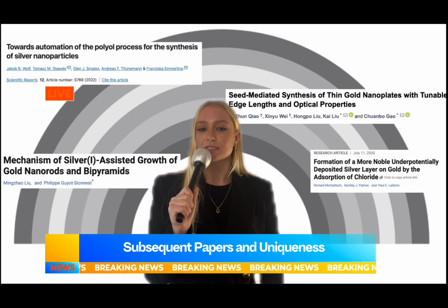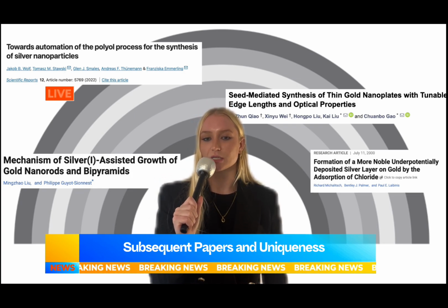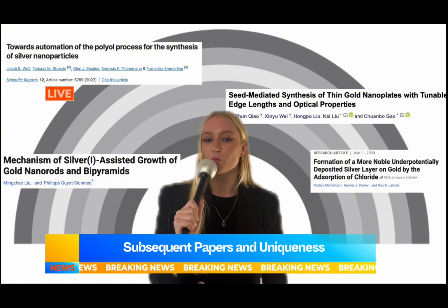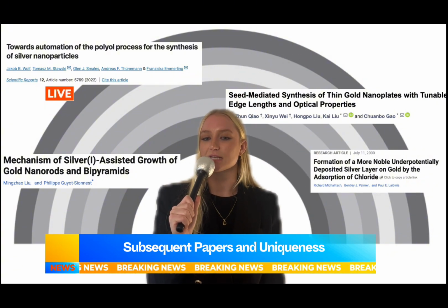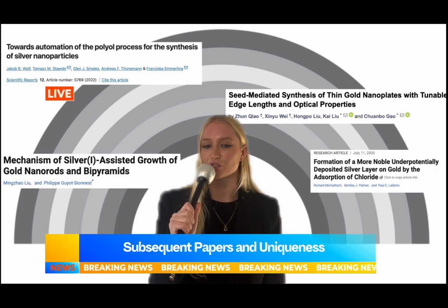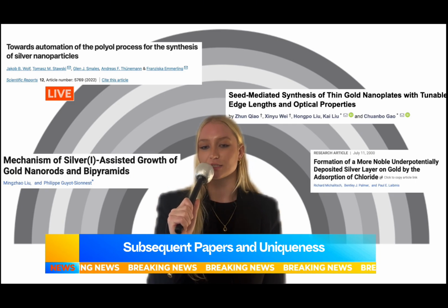Research by Qiao has involved sulfide ligands in halide-free seed-mediated synthesis. Sulfide controls reduction kinetics but also adsorbs onto facets, reducing gold nanoparticle thickness. Research by Wolf and colleagues further explores halide-free synthesis and shows that nanoparticle size is related to a lower ratio of the surfactant to silver ions.